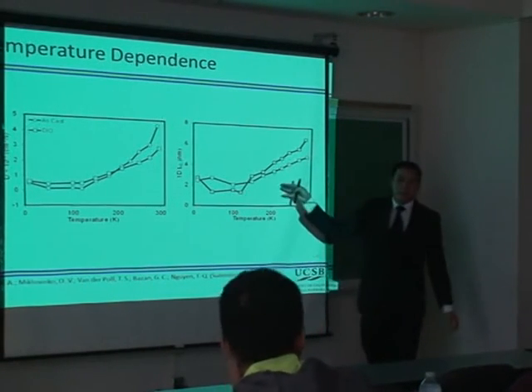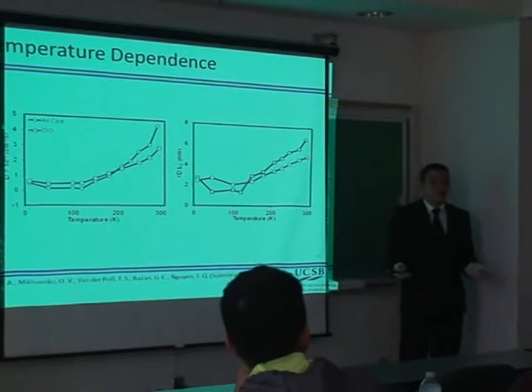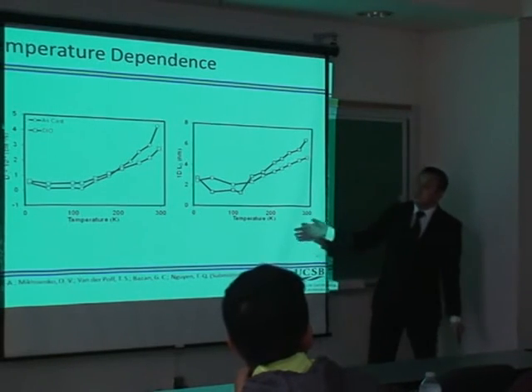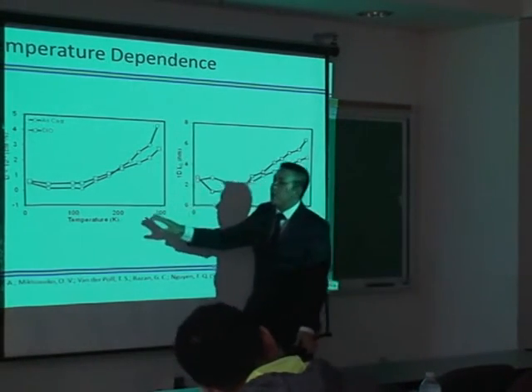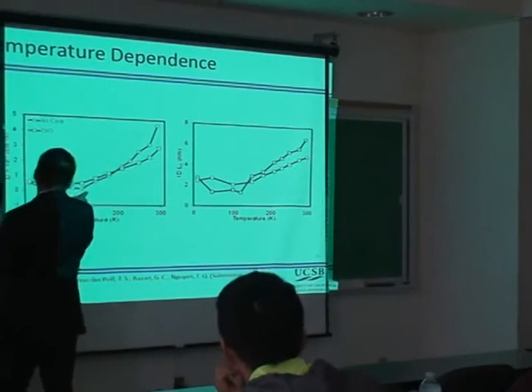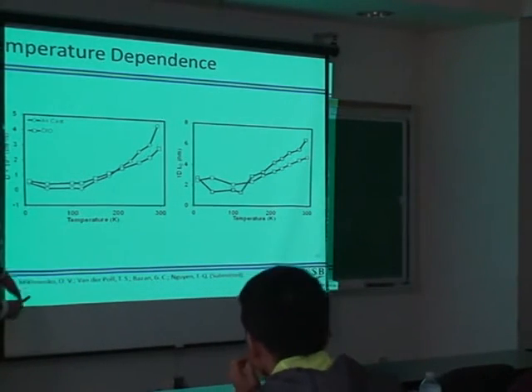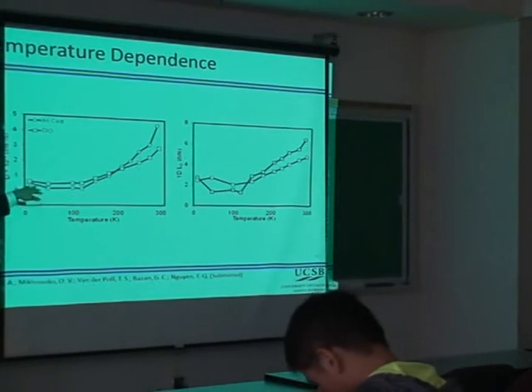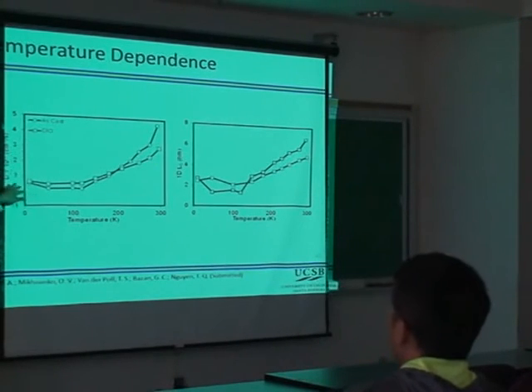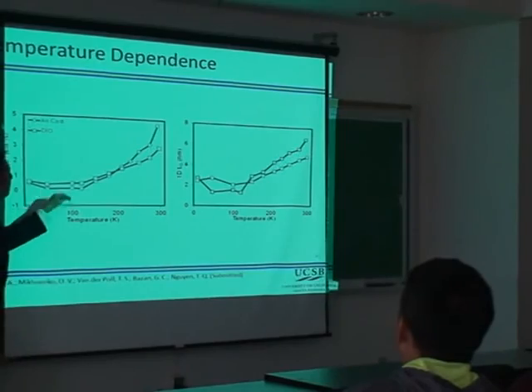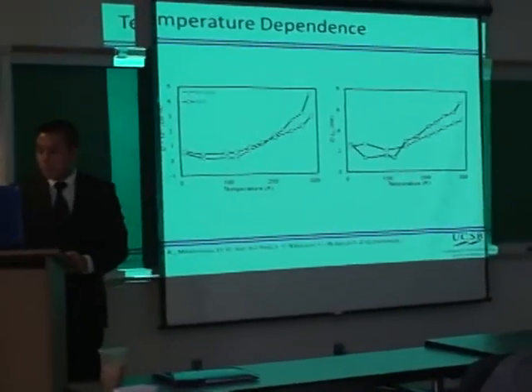And so what this confirmed is that the mechanism is similar to polymers. But one thing that we did find out was unique compared to polymers was that the amount of diffusion in this low temperature regime was actually quite low. The polymers was about 3 times higher compared to this small molecule. So that was one interesting difference that we did find between the 2.